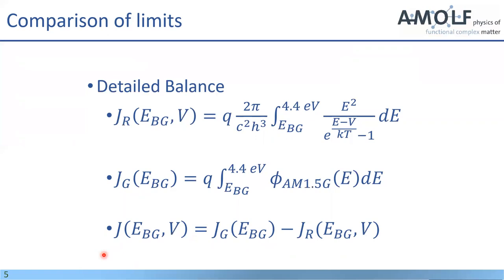And basically, if you want to apply this to a tandem solar cell, you generate those two IV curves, and then put them in series, enforce the current matching condition, and then you can generate a tandem IV curve from those two individual IV curves. And we did this and looked at a couple of different ways of using this limit.